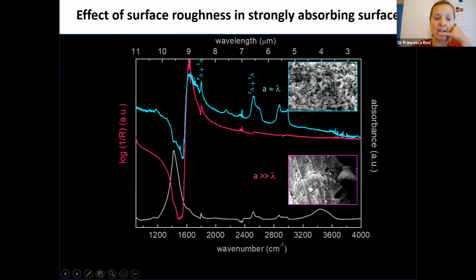Here you see the comparison of a spectrum recorded from calcite in transmission mode. In magenta, you see the reflection mode spectrum recorded with a portable system. You can see that the strong antisymmetric stretching of the carbonate anion appears inverted, better known as the Christiansen band. By simply changing the surface morphology, we have the enhancement of additional bands that normally are not visible in transmission mode, which are the combination bands.